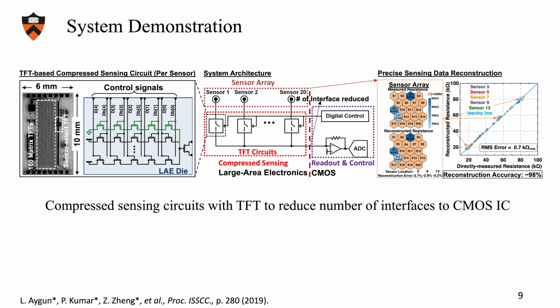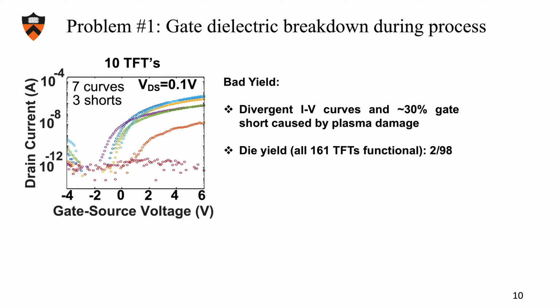The first problem in making such a system is dielectric breakdown during processing. The IV curve shown here is after fabrication. We can see 10 thin film transistors overlaid together with transfer curves, but they have very divergent curves and 30% of transistors are shorted. Also, for the dies, we have 161 TFT circuits per die. The number of dies with all 161 TFTs functional is 2 out of 98, very low. Why does this happen? In this work, we modeled the damage mechanism, validated it, and prevented the damage in experiments.